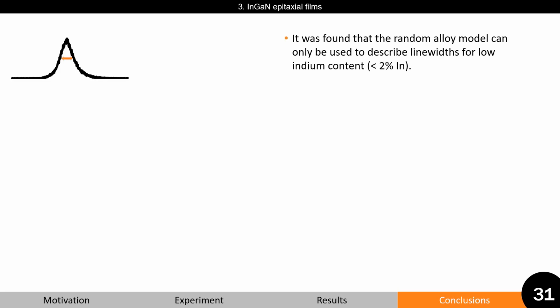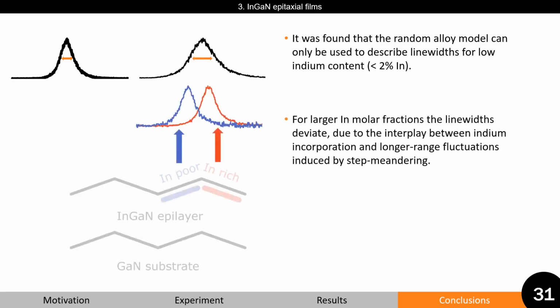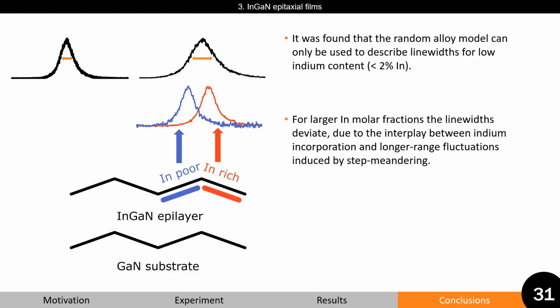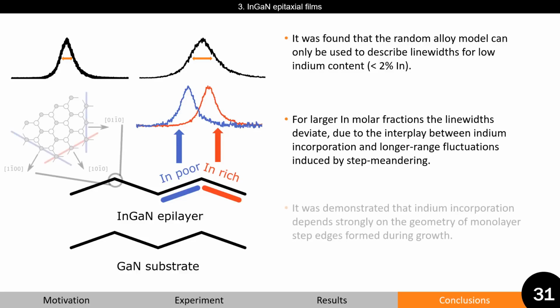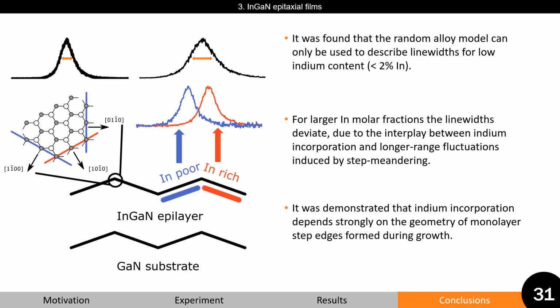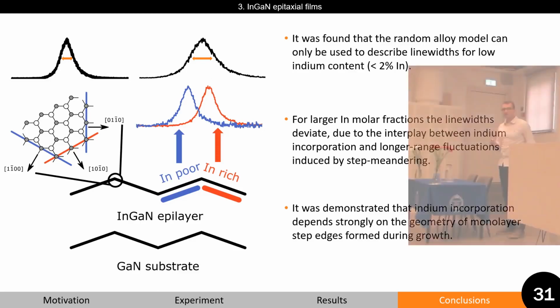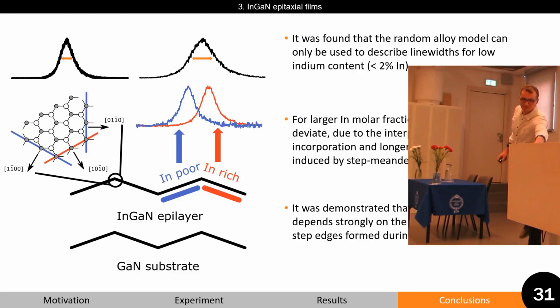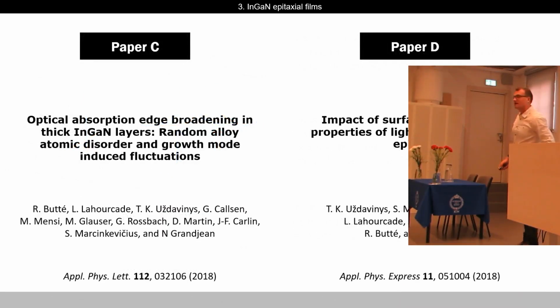Therefore, the main conclusions of the third project are that the random alloy model can only be applied to low indium content samples. For increased indium molar fractions, line widths progressively deviate due to long-range fluctuations induced by step meandering. Finally, it was demonstrated that indium composition strongly depends on the geometry of step edges formed during growth. Results were published in papers C and D.